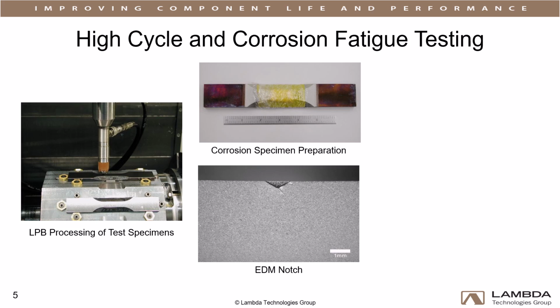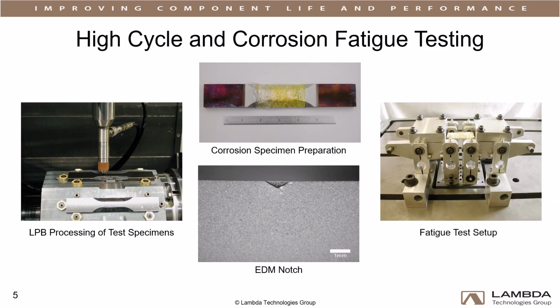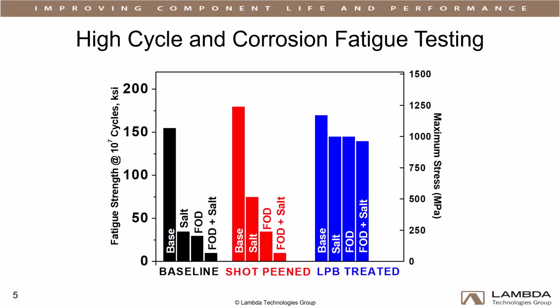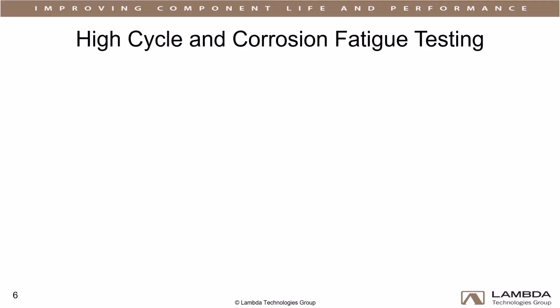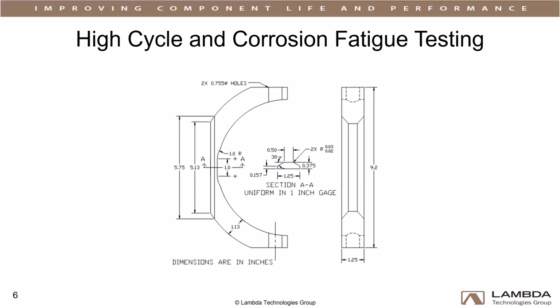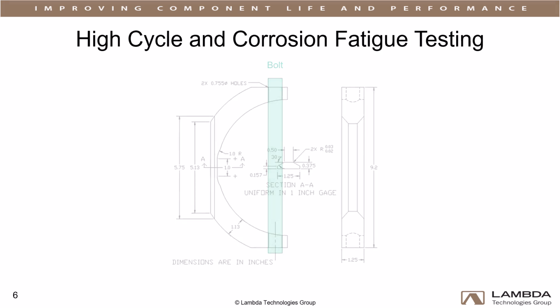High cycle fatigue testing was conducted in 4-point bending on all specimens. Results showed that while undamaged specimens performed similarly under all processing conditions, damaged LPB-treated specimens significantly outperformed both as-machined and shot-peened specimens. Stress corrosion cracking tests were conducted on C-ring specimens made from 300M steel landing gear. A bolt was used to apply uniform tension to the outer surface of the straight gauge section. LPB-treated and as-machined specimens were subjected to alternate immersion stress corrosion cracking testing in a neutral 3.5% sodium chloride solution.